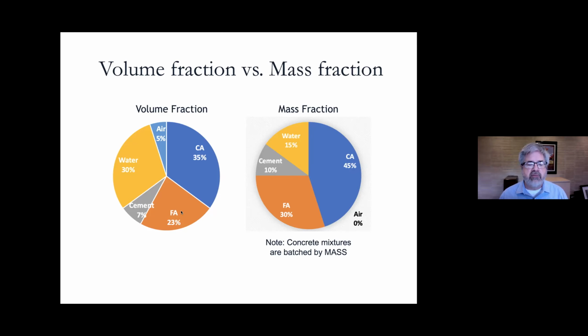Our coarse aggregate and fine aggregate have a specific gravity. Water has a lower specific gravity, and cement has a high specific gravity. So the relative volume of the cement is down. And this little part here, the water and the cement, is the part that is chemically reacting during hydration. And this is the part that creates hydration products that undergo autogenous shrinkage. We're not going to get worried about any volume change in our discussion from aggregate, but we do from the cement side, the cement paste side.